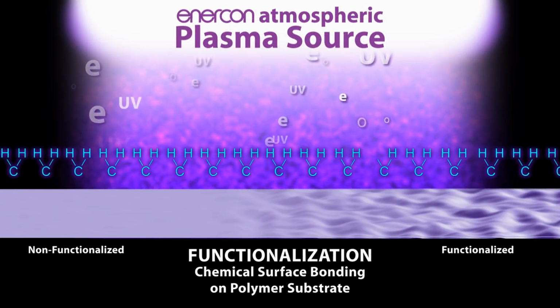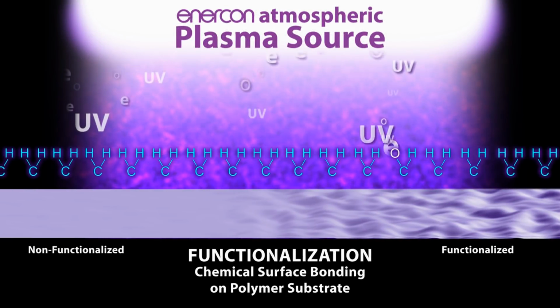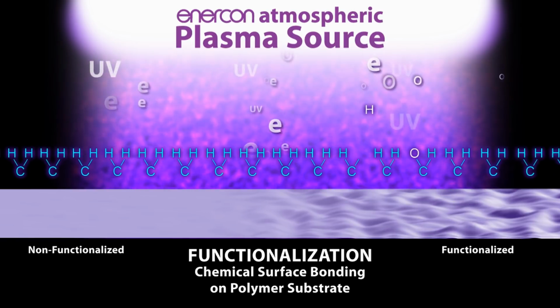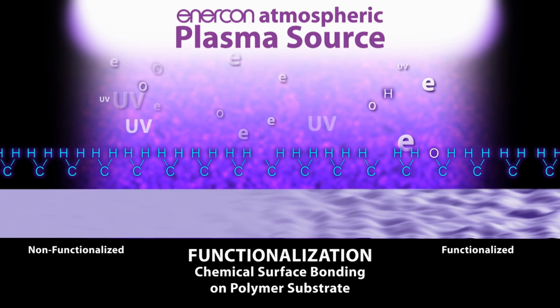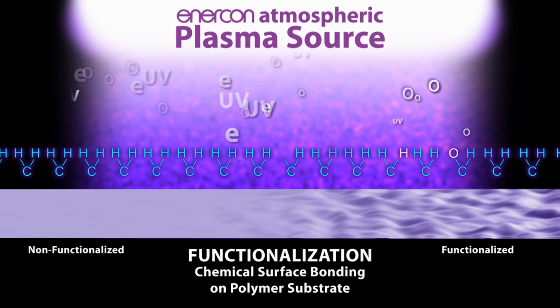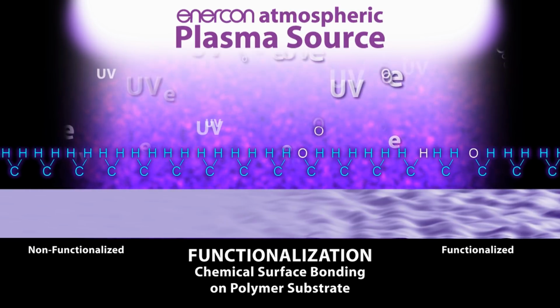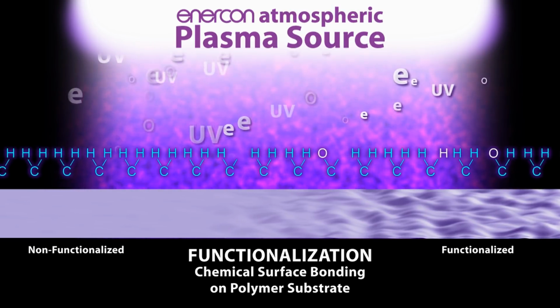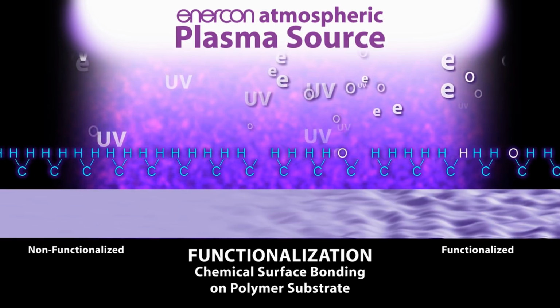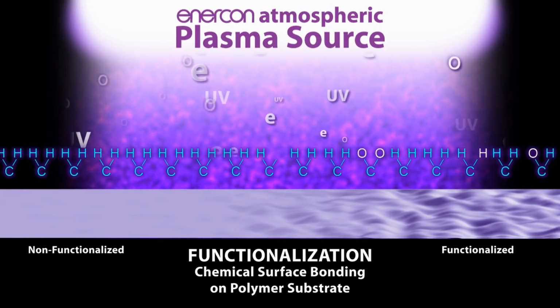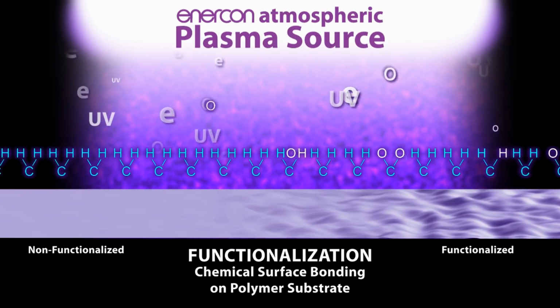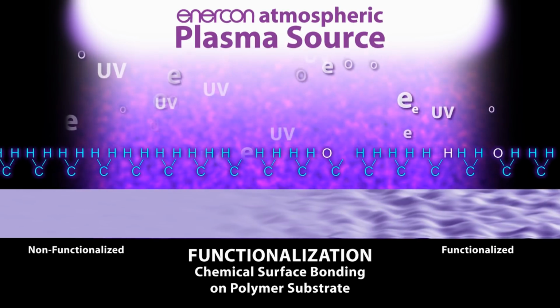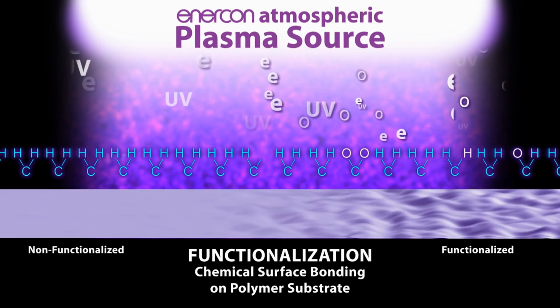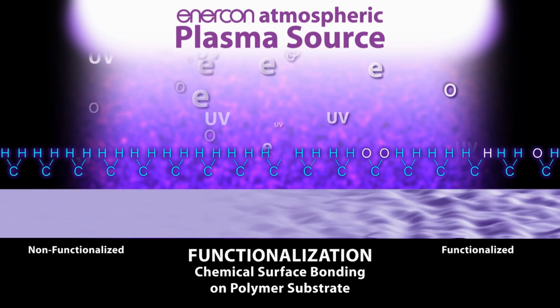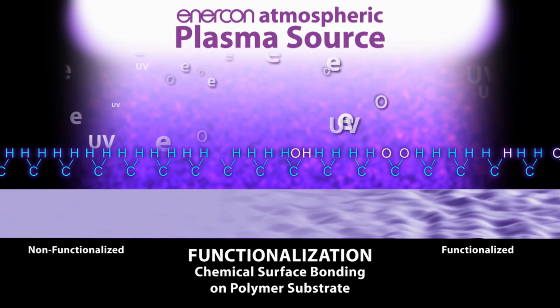Plasma functionalizes your surface. Functionalization, sometimes called activation, means that you are adding hydroxyl or carboxyl groups to the outermost molecular layers of your surface. In this video, you see the ionized gas bombarding the surface. Oxygen groups, OH groups, and hydrogen groups attach to the surface, increasing the surface energy. By adding these polar groups, you increase the overall surface energy and the ability for inks, coatings, and adhesives to improve their bond to the modified surface.